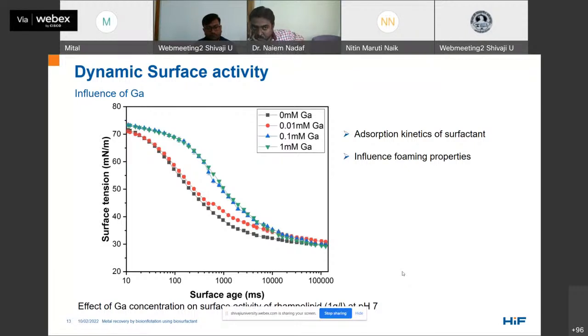Here in the graph, we can see the surface tension behavior of rhamnolipid in the presence of different concentrations of gallium. We can see here that the surface tension curve for rhamnolipid-gallium solutions is much different compared to rhamnolipid alone, suggesting that the gallium metal has some effect on the surface activity of rhamnolipid.